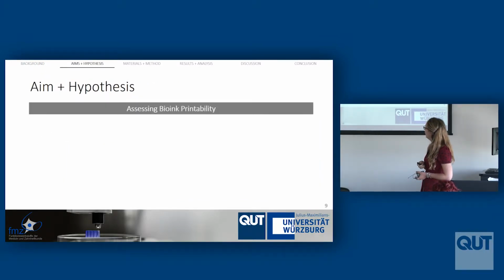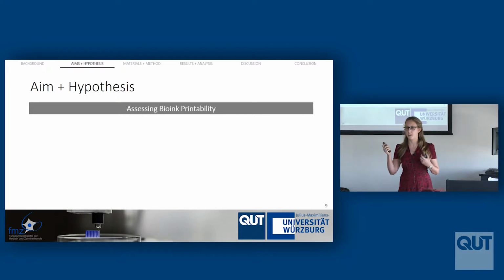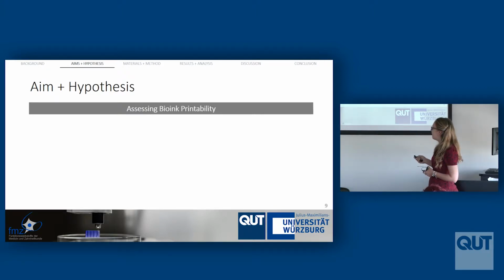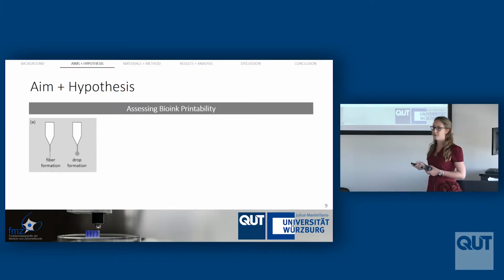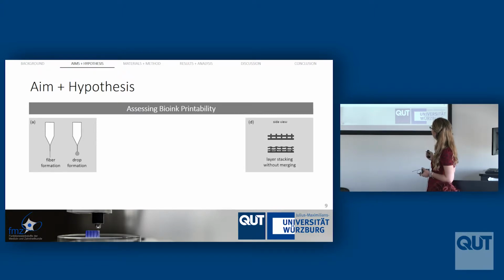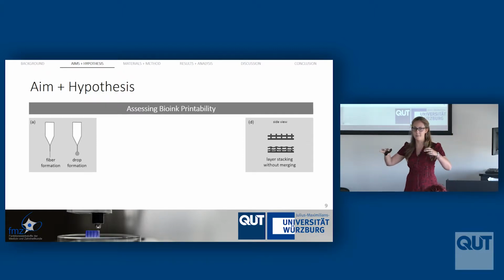So this is what I was looking at. Here is how we can assess bioink printability. How can we tell if a bioink that we're trying to develop is actually going to be printable? So the first thing, we want a fiber to come out of the bottom of our needle here. We don't want a droplet. And so this is what we look for first. And then our second key thing is we want to make sure that we can stack these layers. So this is a side view of our scaffold, for example. Make sure they all stack on top of each other nicely as opposed to all kind of settling down into a shape that's not desirable.